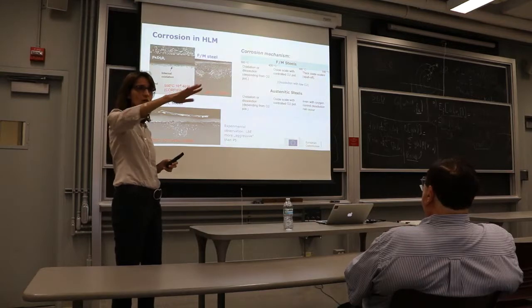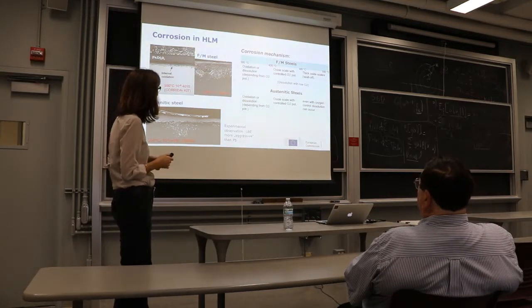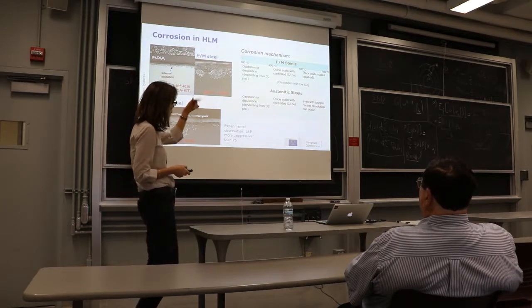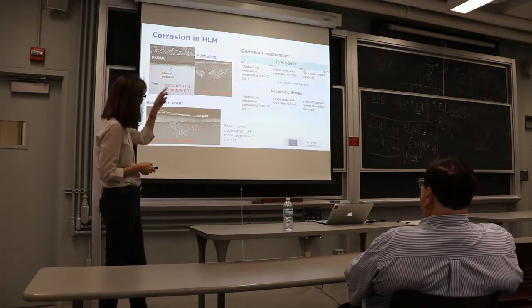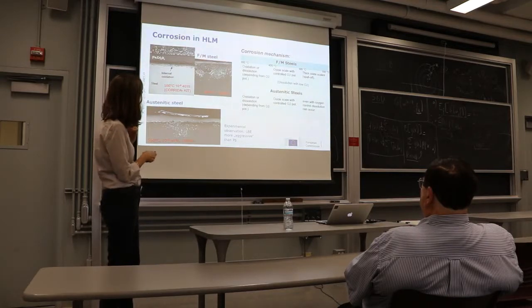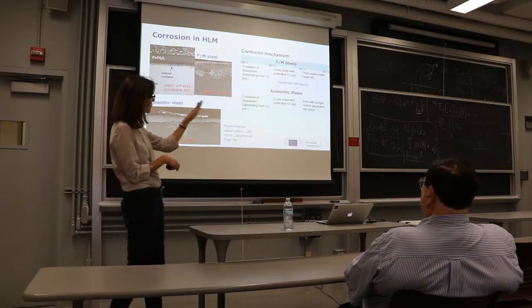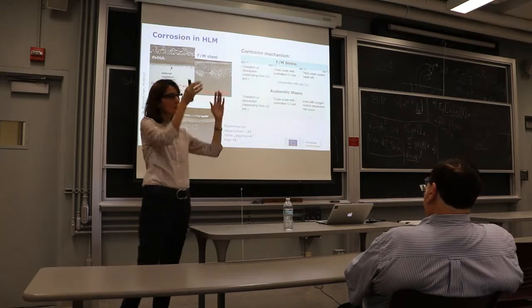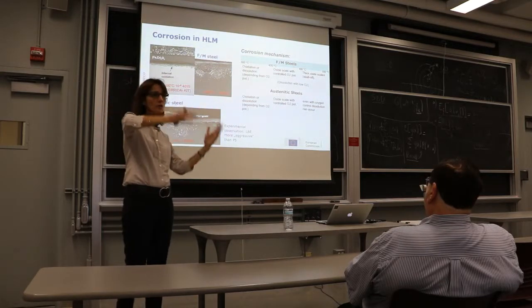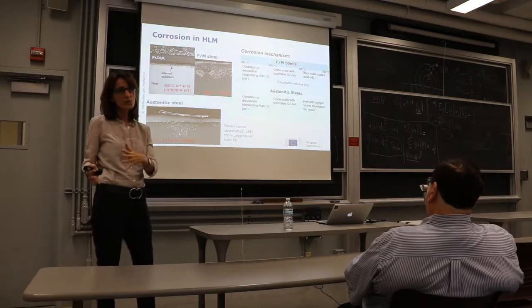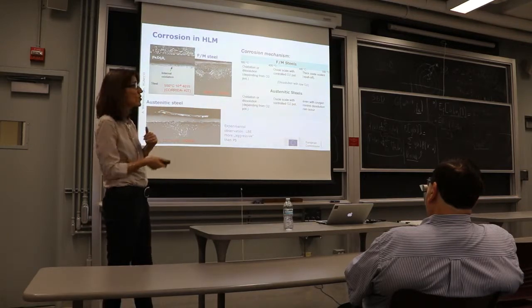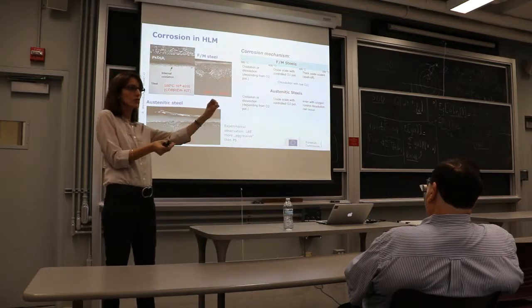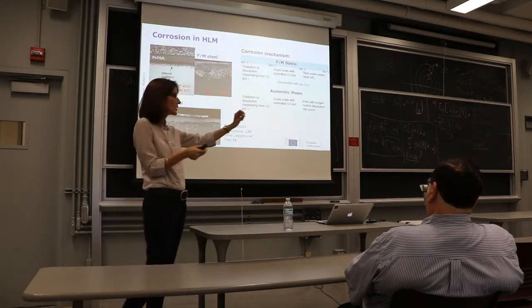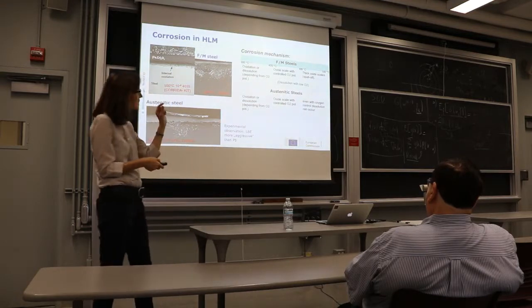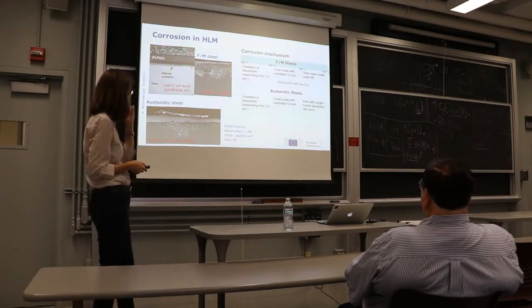So there was a penetration of the liquid metal inside the steel matrix, creating, and I will show you in the next slide, what type of problems this phenomenon creates. And it has been observed on both the ferritic martensitic and the austenitic steel. And what we have tried to do was to identify temperature windows where the material could be used and under which conditions it could be used. And one condition is controlling the oxygen inside the liquid metal in order to let an oxide scale increase on the surface of the steel, but having it not too thick, so controlling also the thickness of the oxide scale.